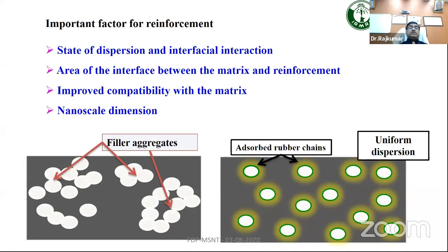Now the most important thing here is the dispersion: state of dispersion, interfacial interaction between the polymer, the rubber and filler, area of interface between the matrix and reinforcement, improved compatibility with the matrix. The compatibility comes with the different matrix and polarity and all. So uniform distribution, dispersion, is the most important. If it is very well absorbed in the rubber chains and uniformly distributed, the rubber strength becomes better, instead of filler aggregates like on the left hand side. With aggregated particles, the interaction with the polymer will be very less, whereas when it is dispersed very well and the surface area is exposed to the entire rubber molecules, molecular level polymers get interaction and the strength will be much better.